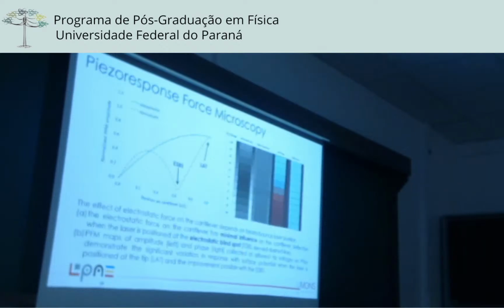So it's extremely complicated. When you're starting with AFM, if you want high sensitivity, it's better to put the laser at the very end of the cantilever to have the maximum energy. But it appears that if you put this spot at more or less 2/3 of the maximum, you compensate the electrostatic force. It is the so-called electrostatic blind spot, ESBS in short, and with that, you almost show that you are measuring correctly. I can show you a lot of papers claiming very huge piezoelectric coefficients that are due to artifacts, because they never measured anything.